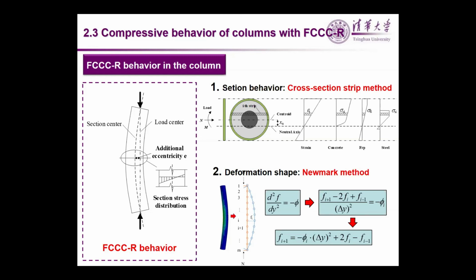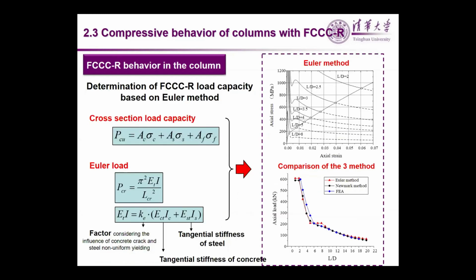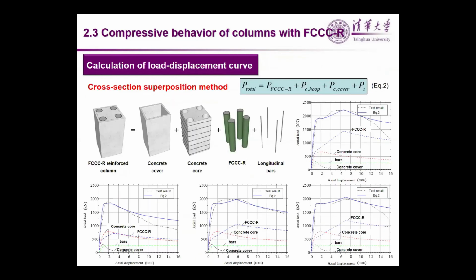So at the end of this chapter, the cross-section superposition method is proposed for calculation of the load displacement performance of the column. And the result showed good agreement with the test result. Moreover, it is noted that the load provided by the FCCC-R is the main part of that of the columns, which surely played as a strong skeleton as we expected.